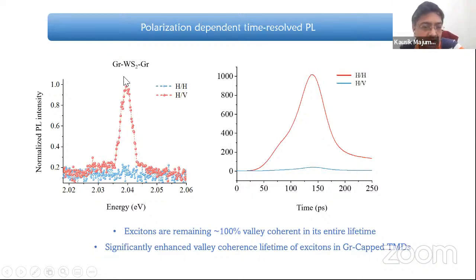Again, we achieved 100% polarization, and we also did polarization dependent TRPL measurements, which show that the excitons really remain 100% valley coherent in their entire lifetime. That's really interesting to achieve, because now it becomes available for many quantum related applications.